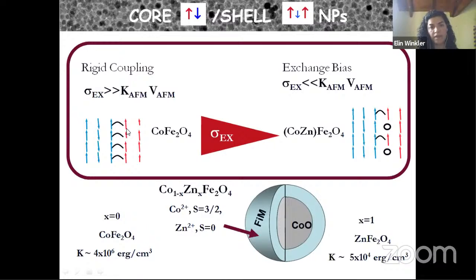Well, replacing one of the magnetic ions by a non-magnetic one. In that way, we are going to reduce this exchange interaction. And how can we do that? Well, by replacing the cobalt, which has a spin of 3/2, by zinc, which has a spin of 0.